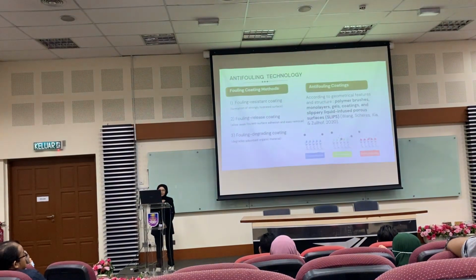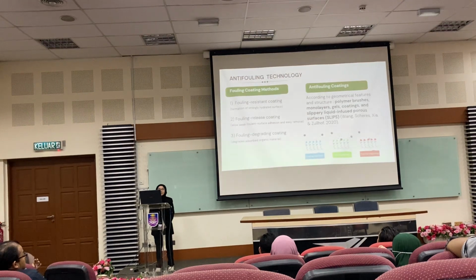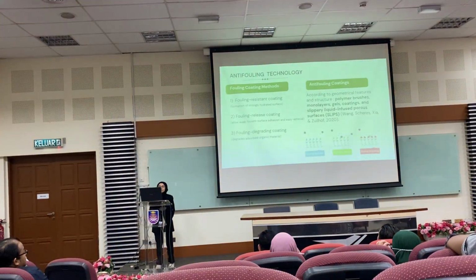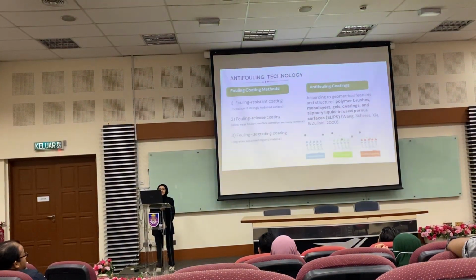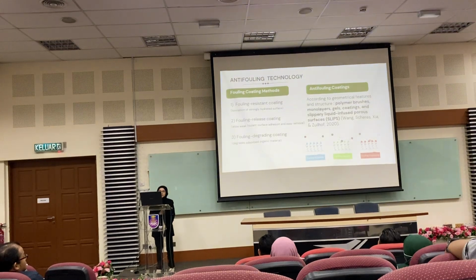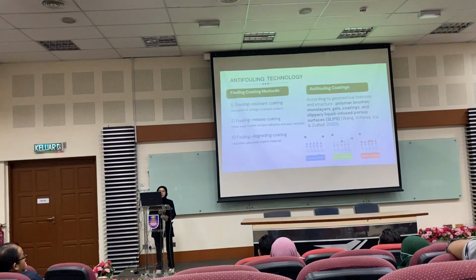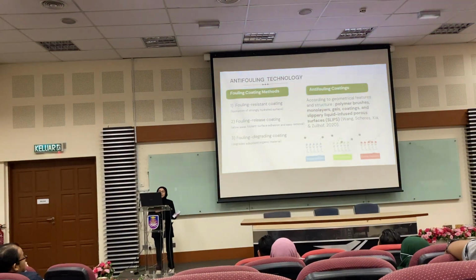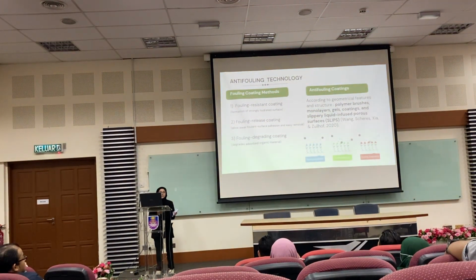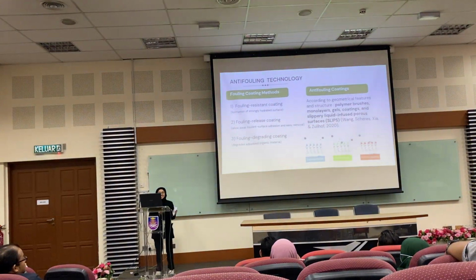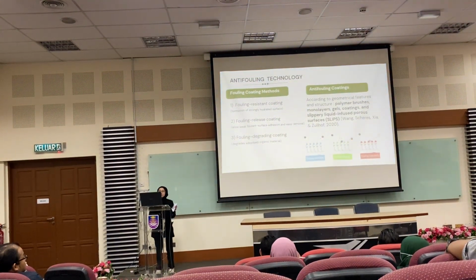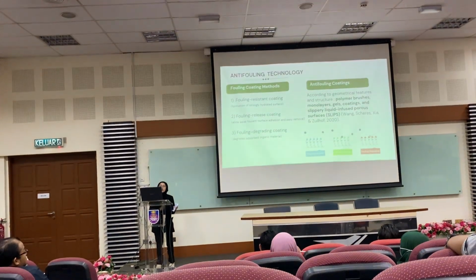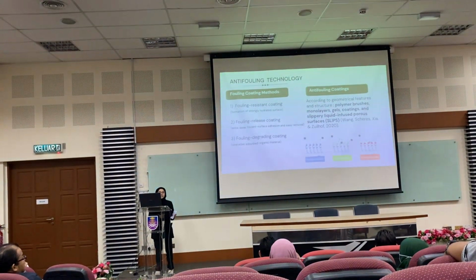There are three types of fouling coating methods, which are fouling resistance, which prevents adhesion of algae and bacteria through strong hydrated surfaces, fouling release, which can be easily removed by limited shear force, like a water jet, and fouling degrading coatings, which degrade the adsorbed organic material through oxidizing agents. The examples of anti-fouling coatings that are popular now are polymer brushes, monolayers, and SLIPS.